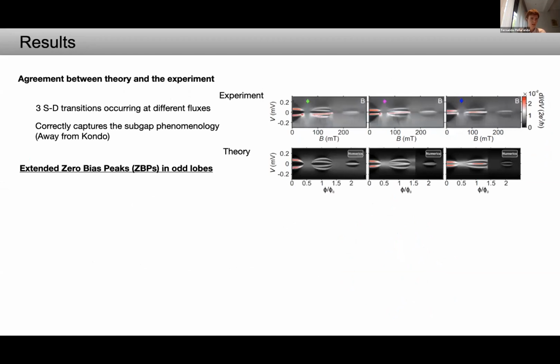So in order to show the agreement between our theory and the experiment, we show 3 different singlet-doublet transitions, which occur at different fluxes due to the fact that the experiment is done on each panel at a different backgate voltage. So the theoretical simulations correctly capture the subgap phenomenology, which is valid away from the Kondo regime, that is, the full superconducting regions.